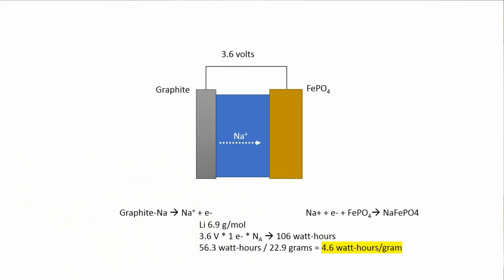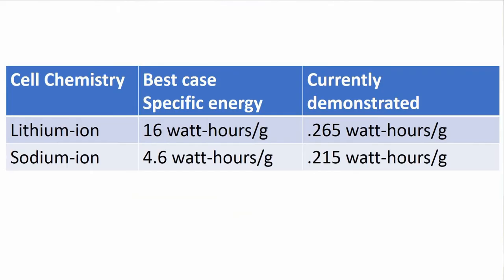It's also why sodium ion batteries haven't had the huge push. Sodium is a lot cheaper than lithium, but sodium is also a lot heavier than lithium. In practical terms, the penalty isn't as bad as it seems just from the weight of the metal itself. The real limiting factor isn't so much the weight of the metal, but rather how much of the metal you can pack into the graphite and other carrier materials. And in the case of sodium, that limitation is a little tighter than in lithium, just because it's harder to fit sodium in between the leaves of graphite than it is to fit in the very small lithium ion.